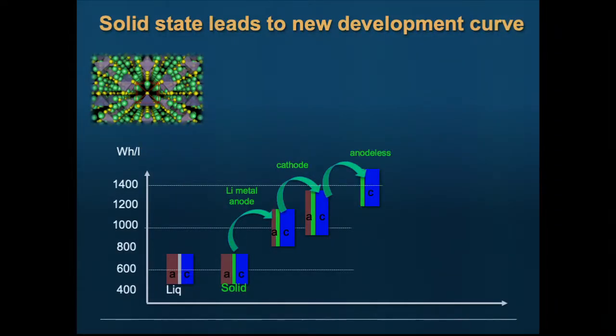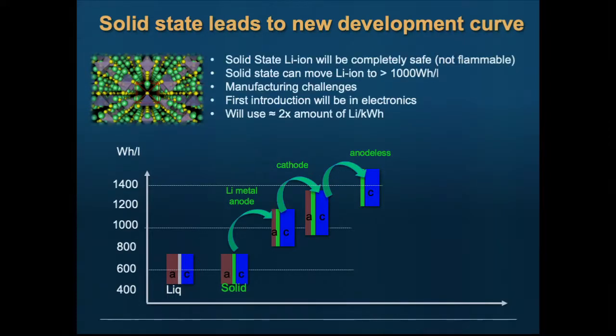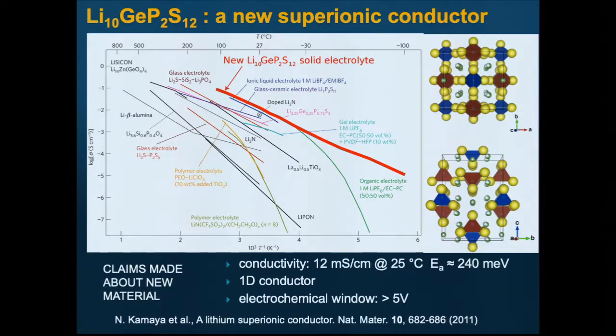The other reason to do this is that we think there's a trajectory to bring lithium-ion from about 600 watt-hours per liter, where it is today, to probably about double, 1,200 to 1,400 watt-hours per liter, if we can use lithium metal anodes. Okay, so what might enable this?